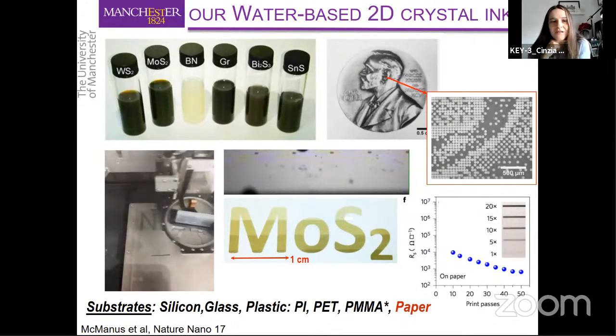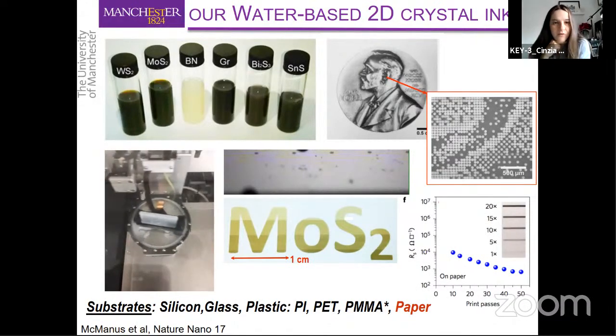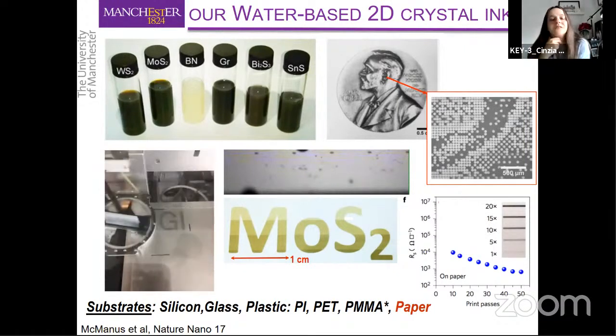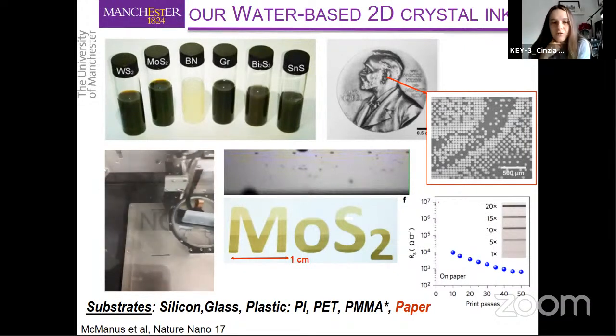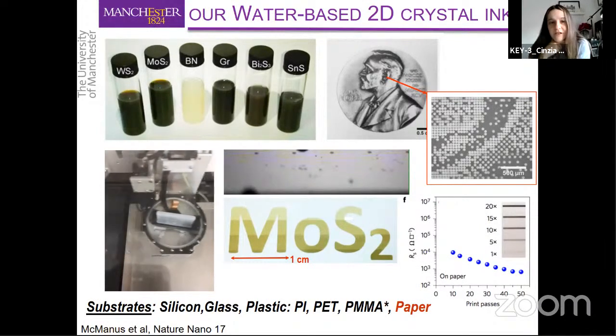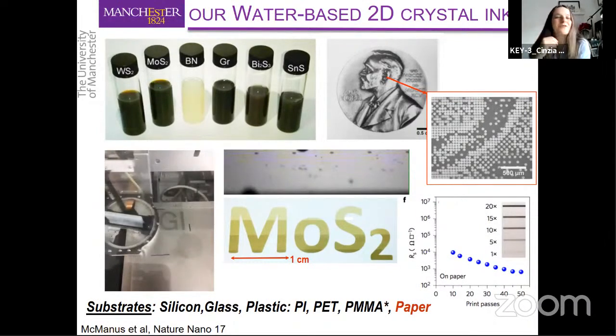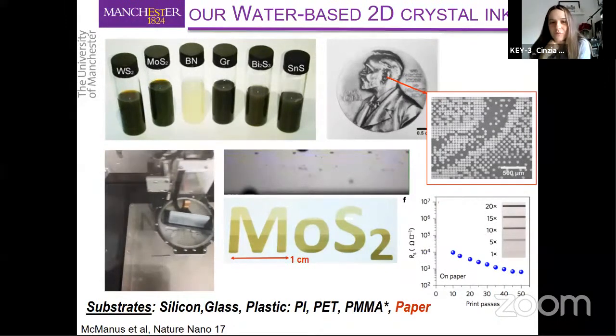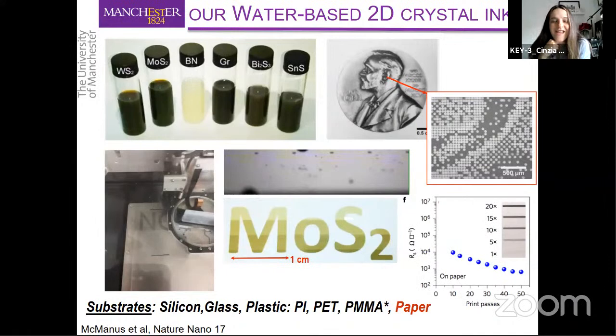And I want to mention here that we are collaborating with several groups to whom we are providing those inks, a couple of groups in the US and several groups in Europe. And so far, nobody ever complained about the printability of the inks. So it's really a robust technology. And we've been able to print on different substrates, but I would say that our preferred substrate is paper. And the reason is obvious. As you know, paper is porous and it can absorb water very easily.